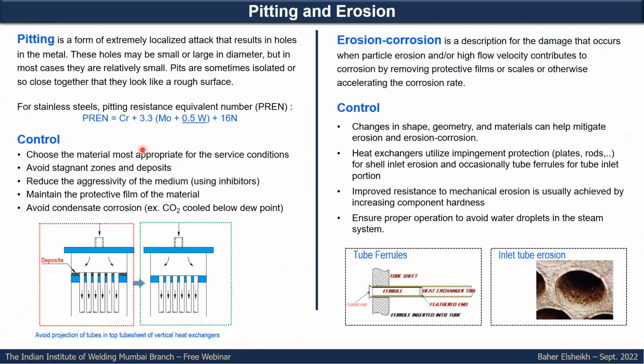For pitting attack, you can see it in the tube-to-tube sheet joint here, and you can think about having a resistant material with a higher pitting resistance equivalent number. To avoid stagnation, it is highly recommended to have the tubes flushed with the tube sheet, especially for vertical heat exchangers, to avoid such deposition or accumulation, which might cause pitting and corrosion in the top face, including the tube-to-tube sheet joint. And you need to maintain the protective film of the material. In many cases, in some services, you might intentionally add some oxidizing material to maintain the passivity, like in some boiler feed systems, or in some applications of carbamate in urea plants. And avoid condensate corrosion, so maintain the temperature higher than the dew point, like in the case of CO2 services.